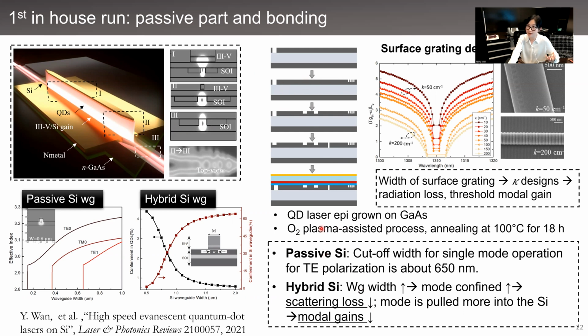there are several things to keep in mind. So first, the cutoff waveguide width for the single mode operation is simulated to be around 650 nanometer for the transverse electric polarization. So we keep this waveguide width in the passive region below 600 nanometer to have a safe margin for fabrication variation in the waveguide width, and especially in the etching depth.